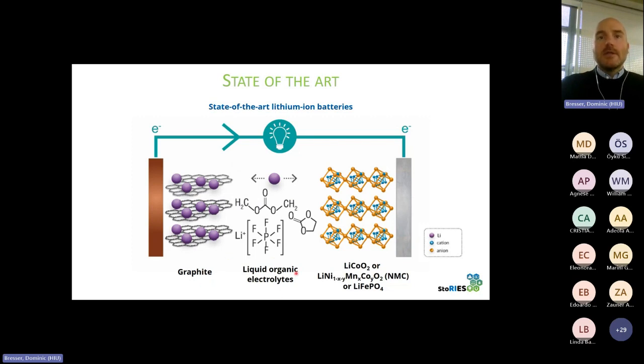Then we have a liquid organic electrolyte, commonly a combination of cyclic organic carbonates and linear organic carbonates, and then some lithium salt like LiPF6, mostly still used. And then at the positive electrode, or cathode, we use lithium cobalt oxide still. So that was kind of this first cathode material and still is used in portable electronic devices frequently.